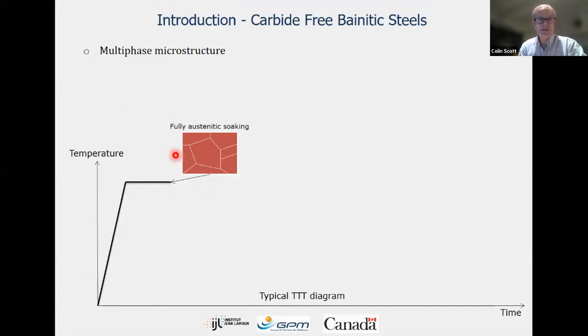So we have to control the austenitization step, and we did it at 900 degrees C. So it's not optimal for, as we'll see later on, dissolving all of the vanadium precipitates, but it does control the austenite grain structure. So that's why we did that.